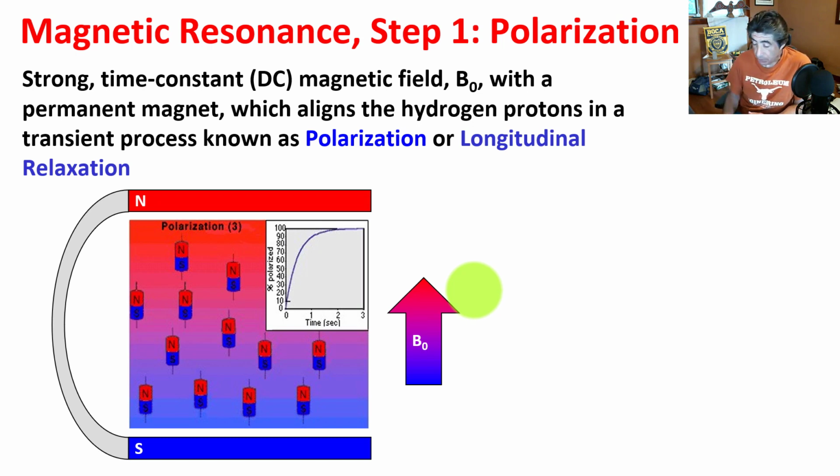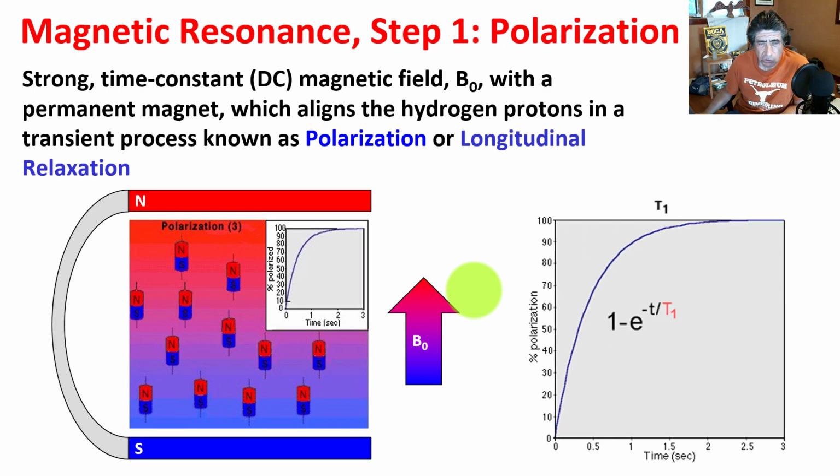And then this polarization causes a relaxation because the polarization is not instantaneous. It takes a certain time before the polarization takes place. And this time, the time it takes for the polarization to be maximum, is governed by the pores, the medium itself, and the fluids. So we have ways to quantify some of the fluid properties based on measuring the speed. For water, the polarization takes place in about 3 seconds.